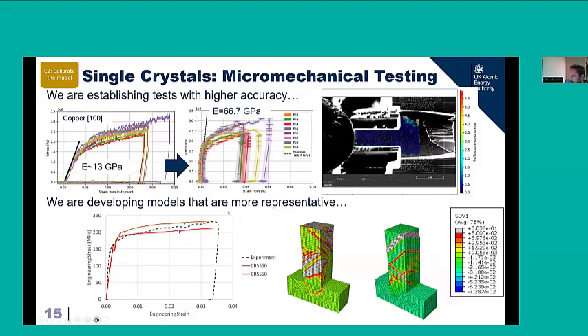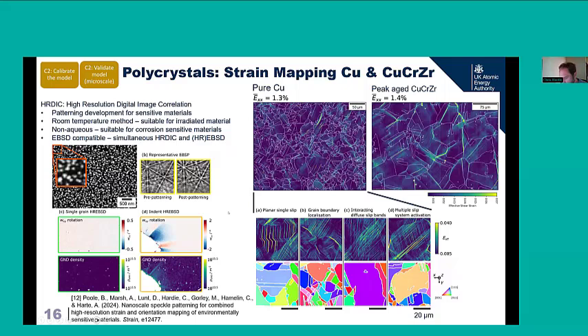Then going up a length scale, once we're pleased that we have a model that represents the single crystal deformation behavior, we look at how the polycrystalline aggregates deform. And here is just another example of the experimental data we've produced. So again, this is an example of high resolution digital image correlation. We've developed patterning techniques that can do this on sensitive materials, that are robust against irradiation, because we're interested in irradiating the samples before and during testing. And also that is transparent to EBSD techniques in the scanning electron microscope.